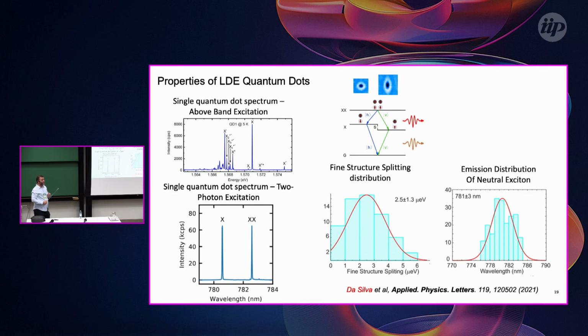Again, in these gallium arsenide quantum dots, you also have the splitting of the neutral exciton energy level. But this time, it does not come from strain, because we are almost strain-free here, but from the symmetry of the confined potential. If these nanoholes are very symmetric, you can grow quantum dots with really small fine structure splitting, on the order of 2.5 microelectronvolts. If you think about it, this is smaller than the linewidth of these quantum dots, which makes these quantum dots, as we say, entanglement-ready for quantum communication applications.